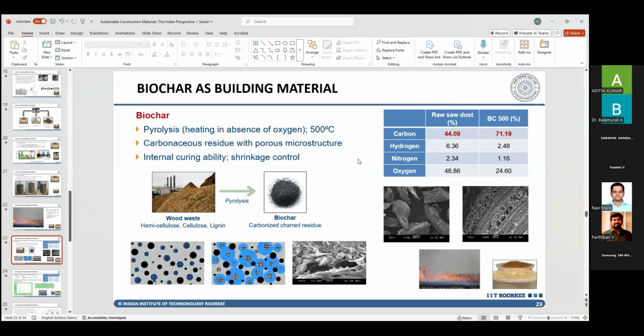The advantage, in addition to all this, is these materials are porous. These are some of the electron microscope images. So you see there's pores in those materials. Now these pores are an excellent site to retain water, and if used in concrete, they can act as what's called an internal curing agent. A material that holds water in its pores, and when mixed in concrete, when the concrete is gaining strength, it can provide water from the inside also. So that's the advantage you can get from a biochar in this, in addition to storing carbon directly inside that char.